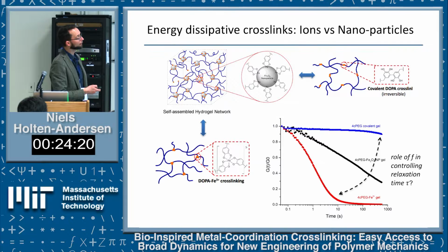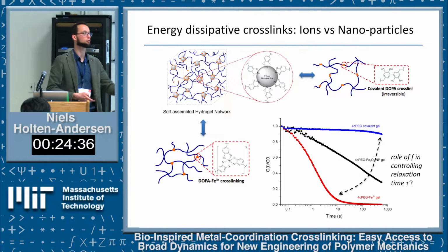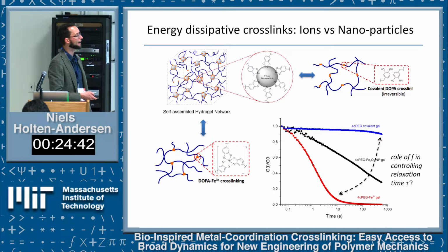...3 different materials behave dramatically different. The permanently cross-linked covalent network will not relax—it'll keep its stress high for hours and should not relax at all unless you break it. The metal ion network will relax on the order of tens of seconds, whereas the nanoparticle network does relax, but much, much slower, and it does so in a controllable fashion. How quick or slow we make this nanoparticle network relax has to do with the number of stickers bound per crosslink.